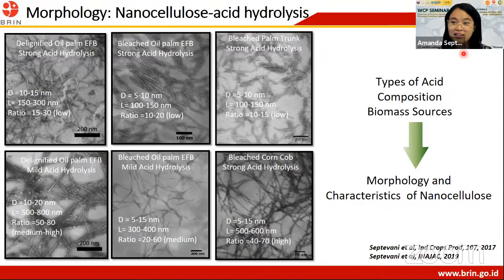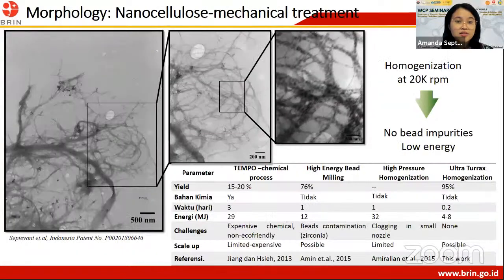So in general, we can say that the type of extraction and the composition of the cellulose, as well as the biomass resources, play really important roles in providing different characteristics and morphology of the obtained nanocellulose. So this is the process to produce nanocellulose via mechanical treatment. We use homogenization up to 20K RPM. And from this, we can compare to the others